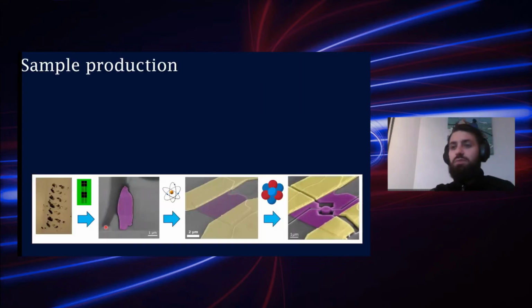So first I will tell a bit about how to create these microstructures. We do this with the mechanical exfoliation method that was developed for the production of graphene. It's also called the scotch tape or sticky tape method, where we take a piece of scotch tape and cleave a larger bulk crystal into crystal flakes, and these crystal flakes we are able to deposit on a substrate. Next, we use e-beam lithography to contact these crystal flakes, and we can do transport experiments on them.